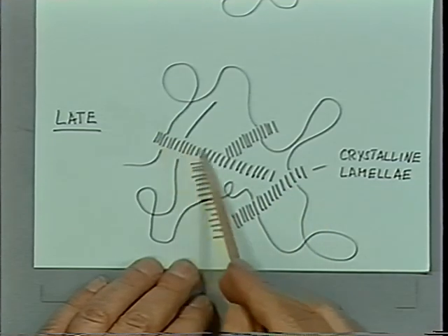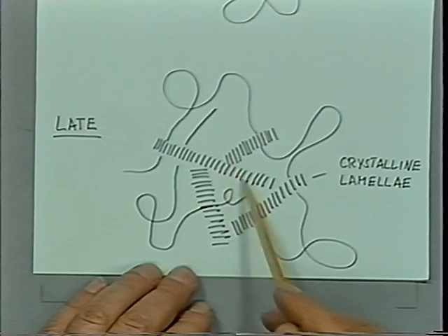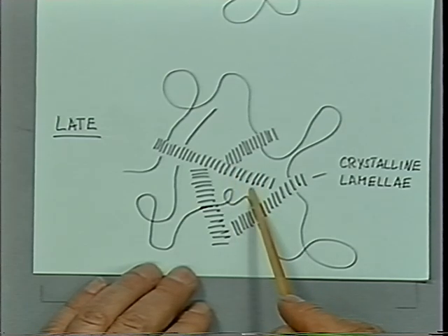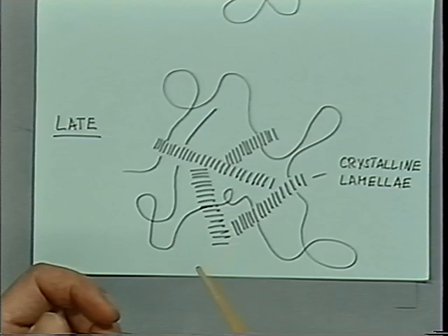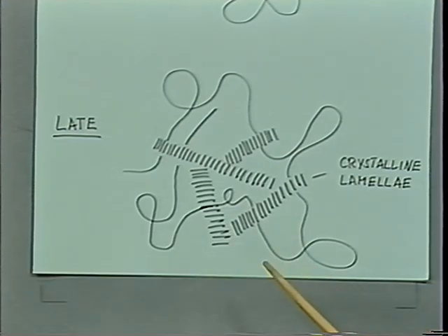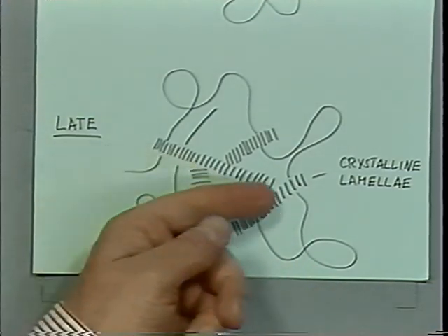And you also have a stiff network because those lamellar regions are contacting each other, and you have to break those first when you deform the material. So that breaking, this initial breaking, is a characteristic of those gels. I will come back to this with the second example. And the first example, I don't have mechanical properties.